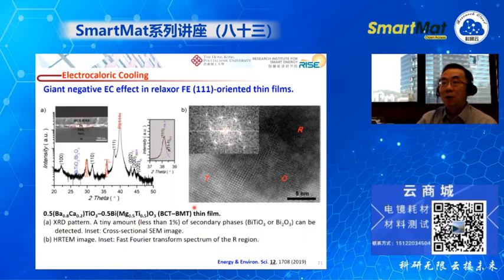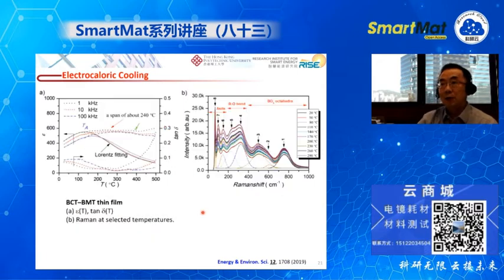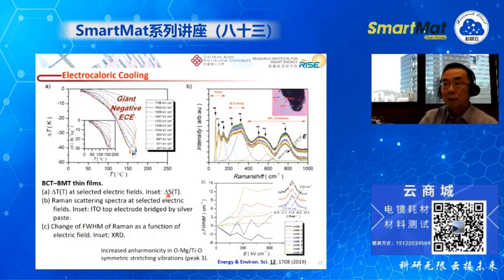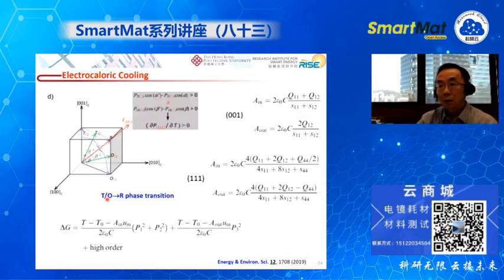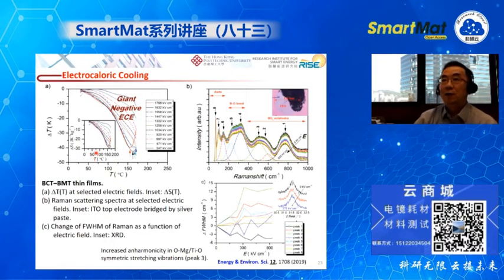And similarly, we also did another work by choosing this type of material, BCT-BMT thin film, and we fabricated this film with 111 preferred orientation. This material was characterized to have ferroelectric phases and with relaxor behavior. And the feature of this material is when we apply electric field, we found a phase transition from the initial tetragonal and orthorhombic phase finally to the rhombohedral one. And we also observe a very large negative electrocaloric effect.